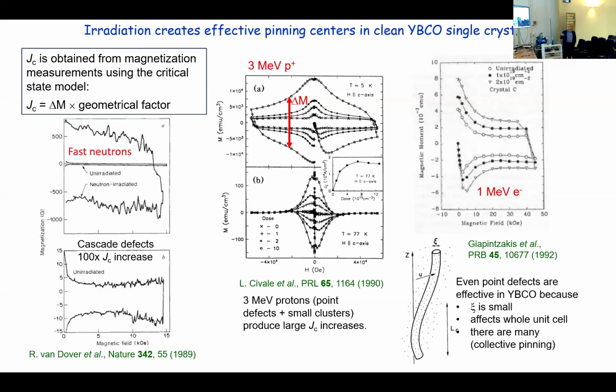So these are three examples. These are magnetization measurements. The critical current is extracted here from the width of the magnetic hysteresis using a geometrical factor. This is the critical state model. It's very well known. The first spectacular measurement was this report. This started on day one of the high Tcs, but initial measurements in polycrystalline materials were not that clear to interpret. But as soon as people had single crystals, there was a pioneering work by Van Dover and co-workers at Bell Labs in 1989, where they used fast neutrons to irradiate YBCO, and they saw an increase of a factor of 100.